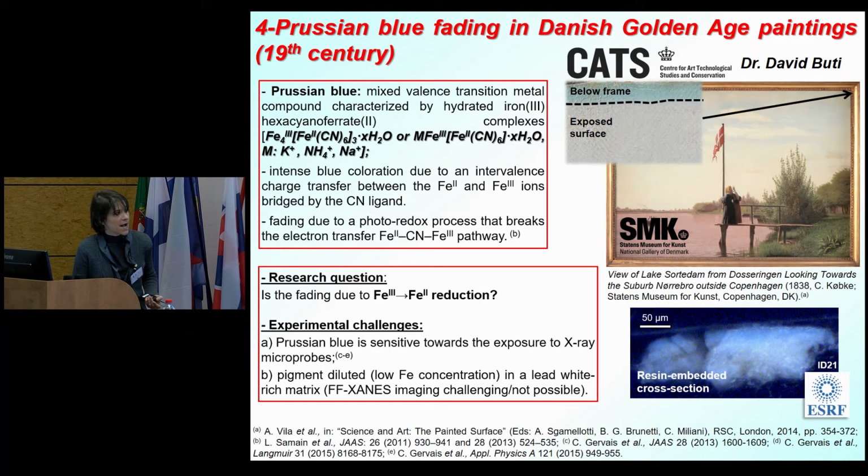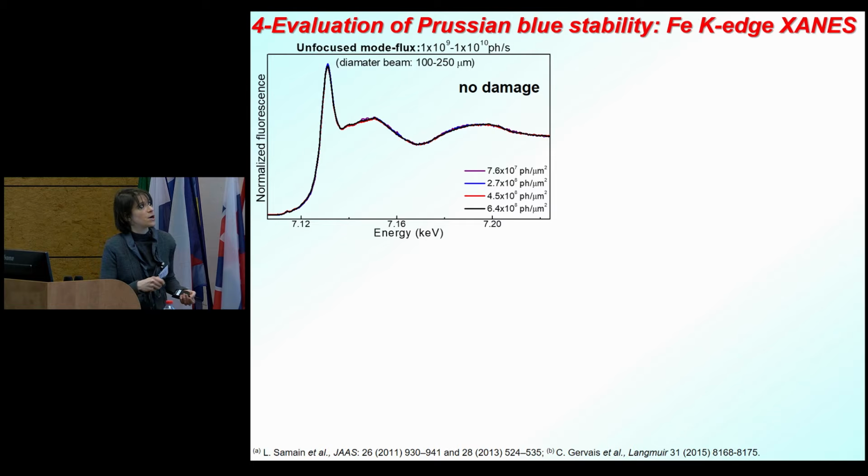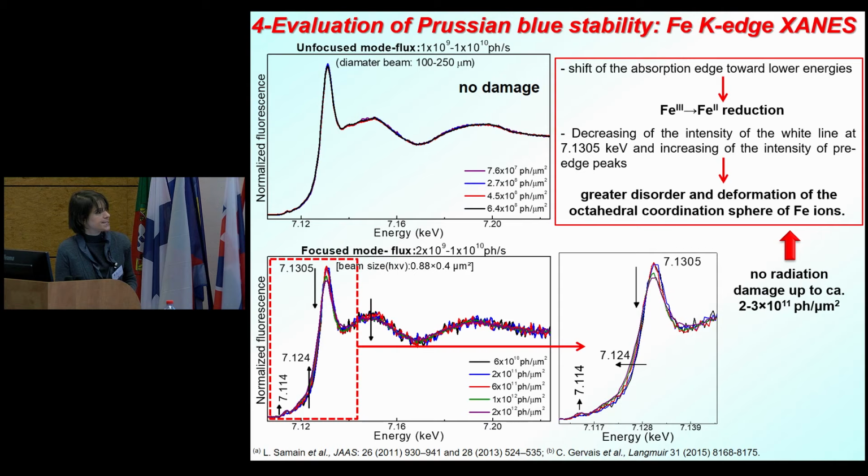We studied a series of resin embedded cross sections, but taking into account this sensitivity, first of all we did some tests to evaluate the stability of Prussian blue under exposure to the X-ray beam. By using an unfocused beam, with this range of fluence values, nothing happened. You can clearly see that the spectra remain the same. But what happened when we used a very microfocused beam, the same that we usually use for studying microsamples? You can clearly see that the spectra, just after one acquisition,